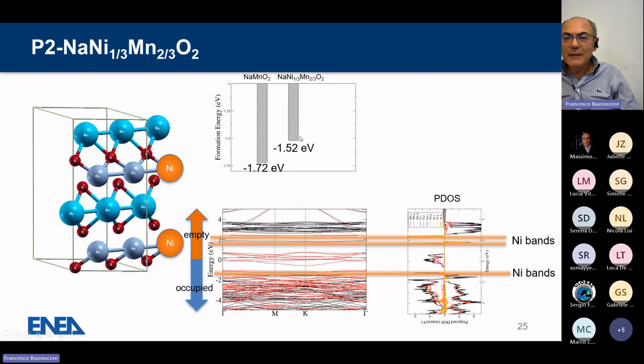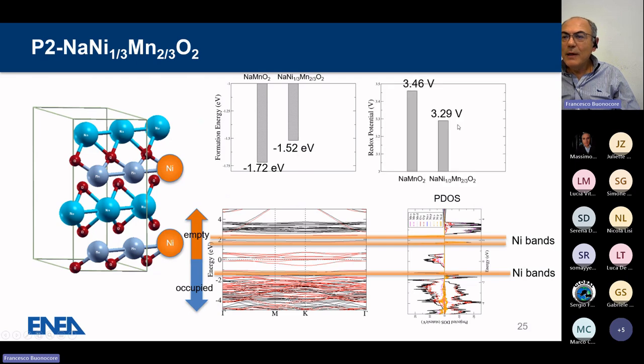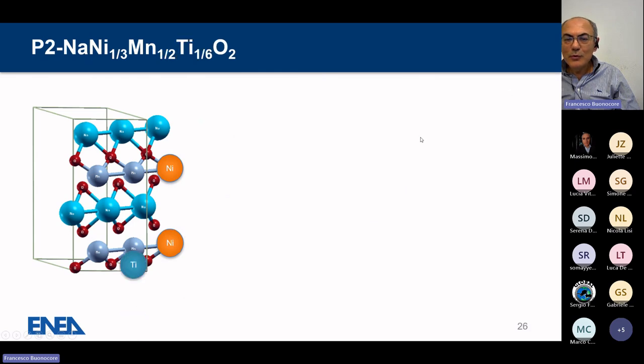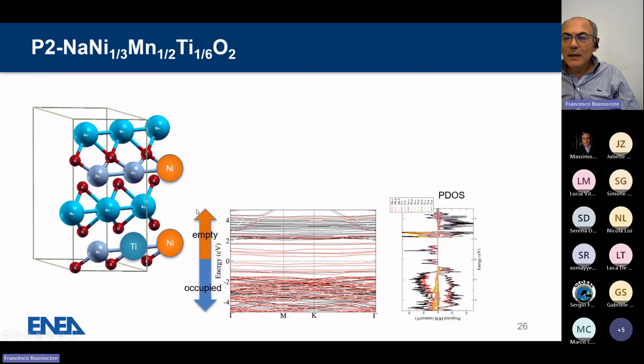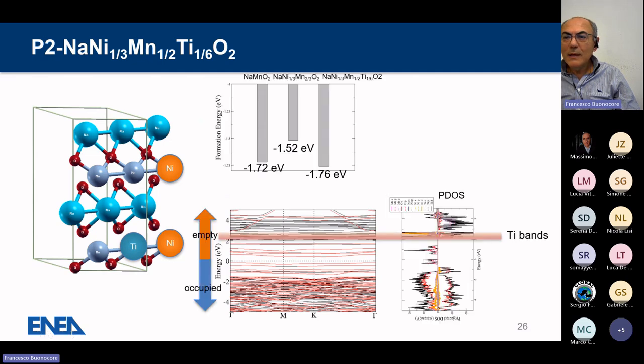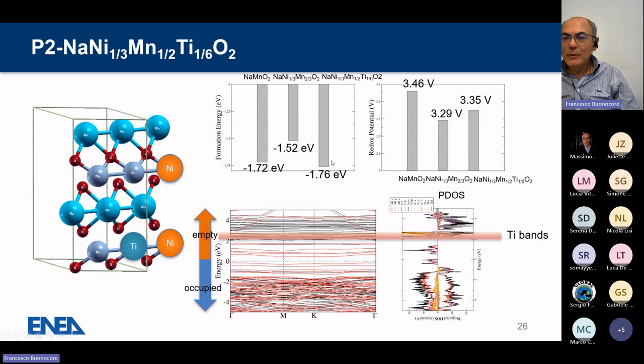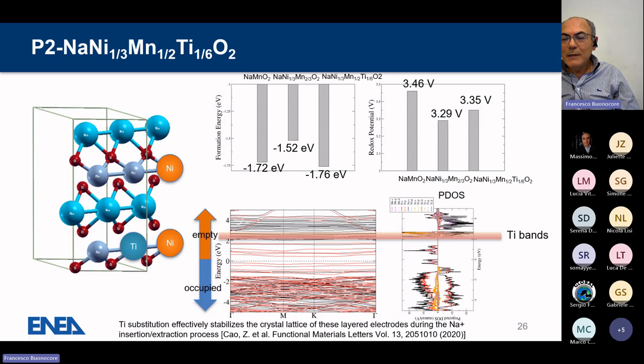In this case, the system is less stable. We have a new intercalation potential, and then we also substitute one titanium atom. In this case, we have titanium bands, and finally we found that when we substitute titanium, the system is more stable. Anyway, this is just a limited selection of crystals. We would like to explore more and more crystals. It's not sufficient to study 3 crystals to say this is the most stable crystal that exists.